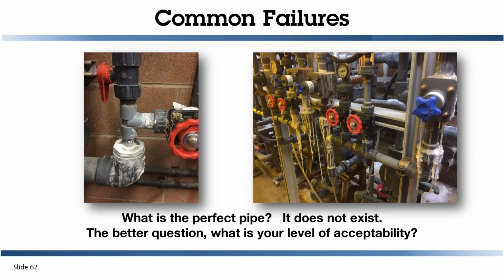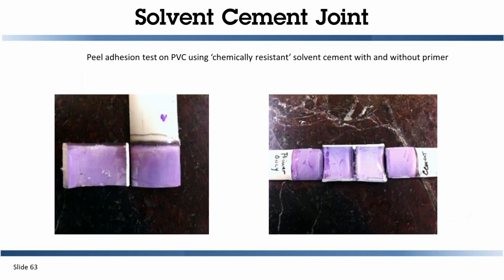So why does the PVC tend to fail with bleach applications? When it comes down to it, a solvent cement joint is nothing more than a cemented fitting. We have separation here. This is a peel adhesion test where we're taking the coupling and we're just peeling it back off the pipe. If we were to do this on polyethylene or polypropylene, you would actually have the pipe and the fitting peeled back together and ripping. So this is one of the common areas of failure because it's so available. People are using PVC where it's maybe not necessarily chemically resistant. And so education on the proper thermoplastic and proper installation method will really reduce this in the future.